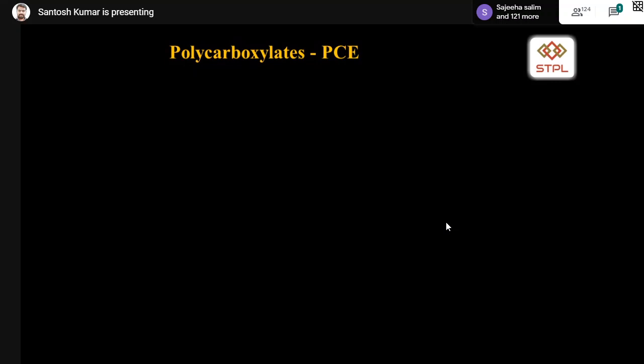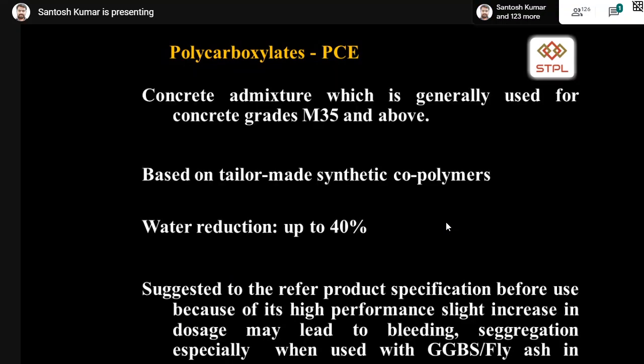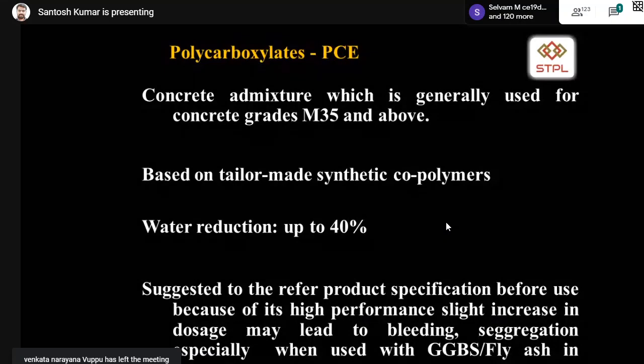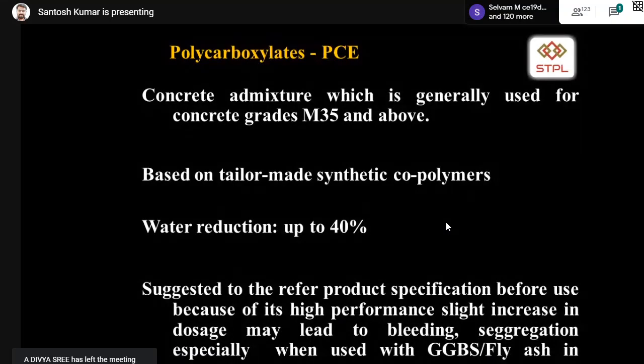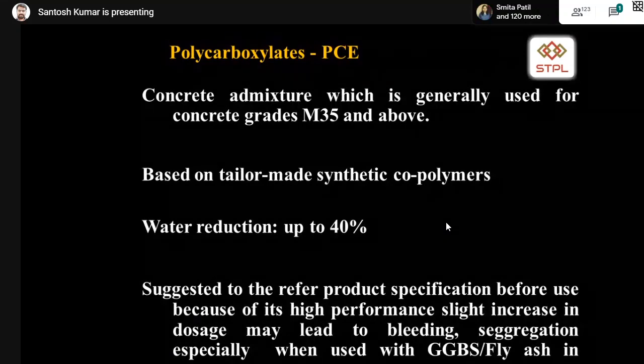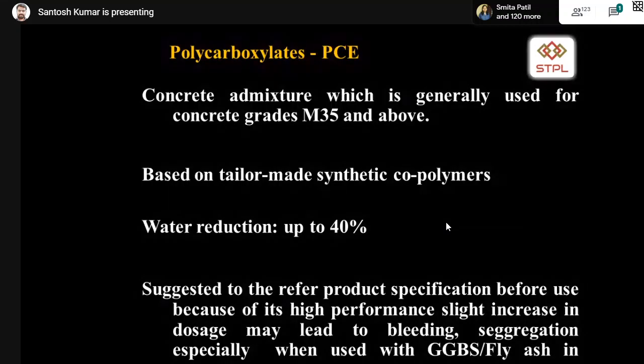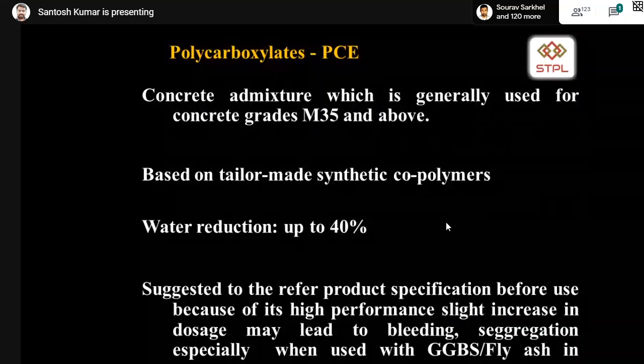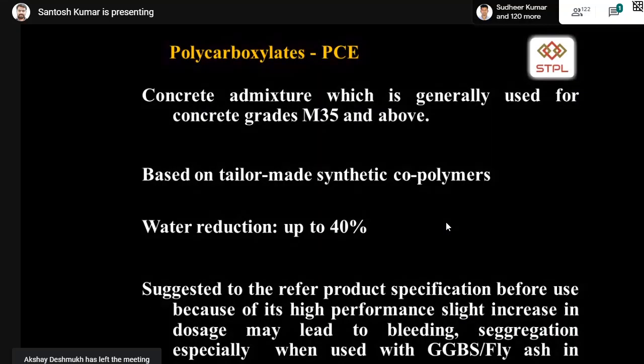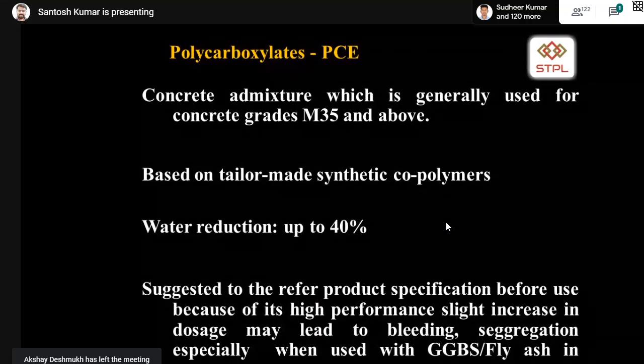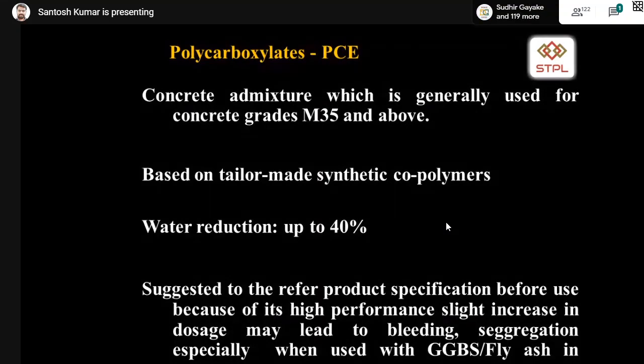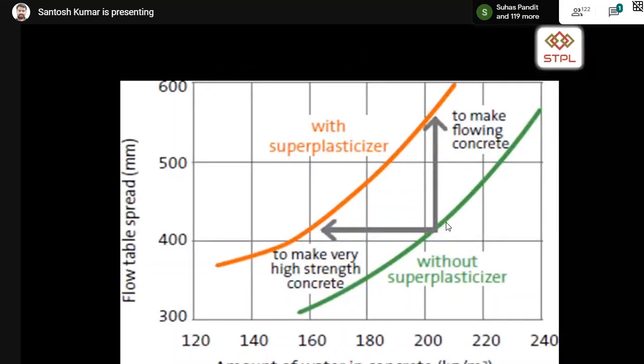Now, another type basically used is polycarboxylate ether-based admixtures, and these are preferred above M35 grade, and they are based on tailor-made synthetic copolymers. Especially, the water reduction can be taken up to 40%. But here, one thing I want to suggest is, while buying or using these polycarboxylate ether-based admixtures in your concrete, please refer to the product specification or the technical data sheet of the admixture before its use in high strength concrete, because if you slightly increase the dosage by even 0.1% by weight of cement, it may lead to bleeding, segregation, especially when it's used with GGBS and fly ash in concrete. So PC admixtures are very sensitive and it should be thoroughly understood before using it in your concrete.